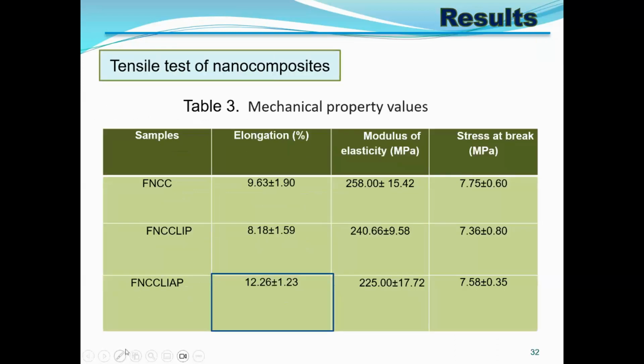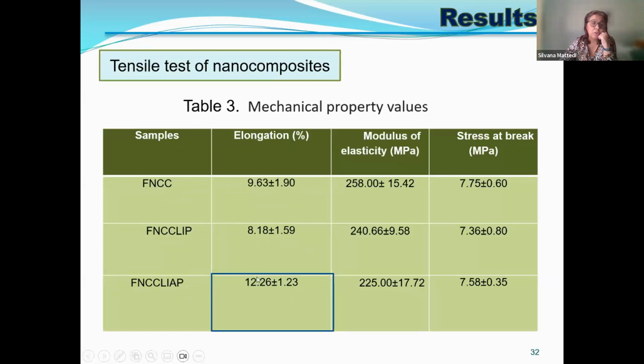And also, they do have mechanical properties, and the mechanical properties do not vary so much. Elongation, which is very important for processability of the material, is much better with the imidazolium. But for the other, it's a little bit better. But for stress at break, it does not change very much, and also the elastic modulus. Thus, the variation is not that important.